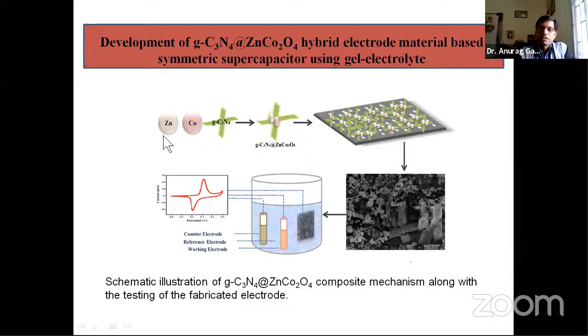And then firstly, we will make the zinc cobalt oxide by adopting any simple technique, either sol-gel method, co-precipitation, hydrothermal, whatsoever. And then you can make some graphitic carbon nitride, mix both of these two and do some heat treatment. Finally, once you prepare this composite, it has to be spread over this nickel foil, nickel sheet, and then this electrode has to be prepared and tested for the electrochemical reactions.